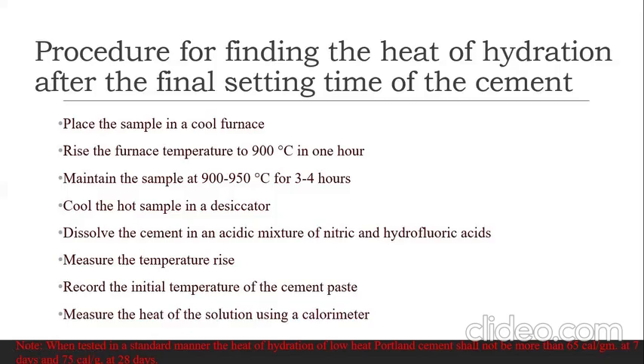For example, after 7 days, the heat of hydration should not be more than 65 calories per gram. And after 28 days, the heat of hydration should not be more than 75 calories per gram of cement.